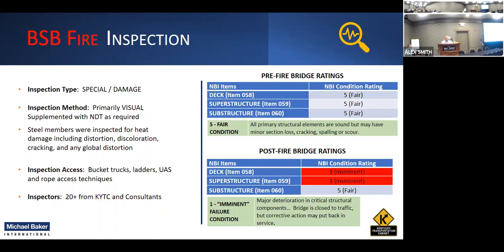So all in all, after our inspection, the bridge, prior to the incident, we had it all at 5 on the deck, super and sub. But we knew there were still some issues with that steel because it was a fire, it still got hot. So we ended up taking the deck and super to a 1 unit condition for an NBI rating. And we thought that was pretty fair considering what we were seeing. Of course, we did inspect all the steel members for heat damage, distortion, that kind of stuff. And as I mentioned here, y'all can read that, the inspection access we had, over 20 people, including KYTC and consultants. It was a big hands-on deck.